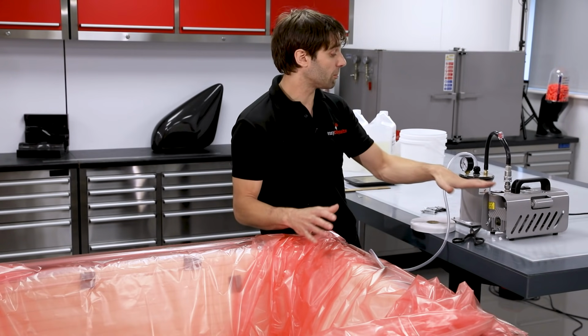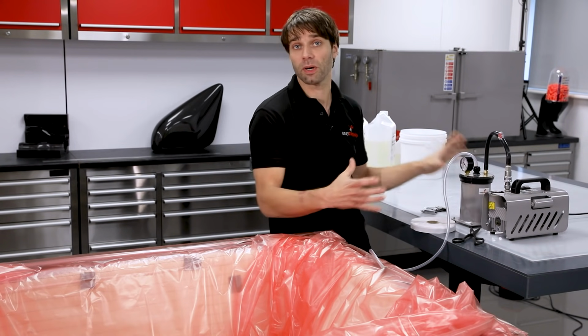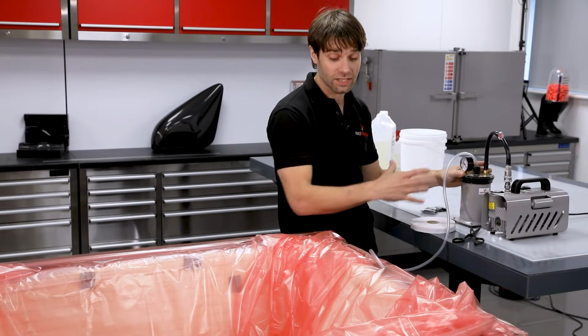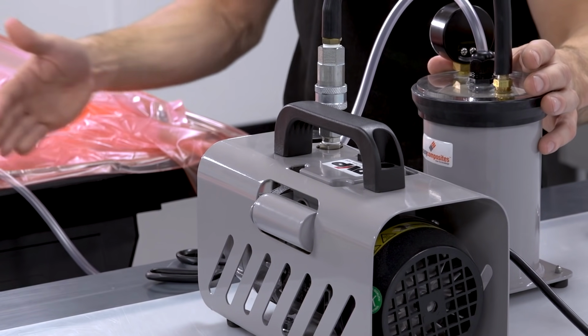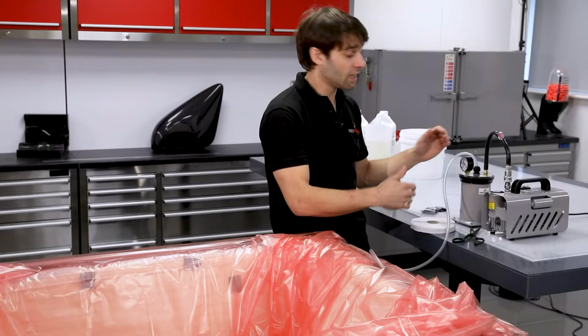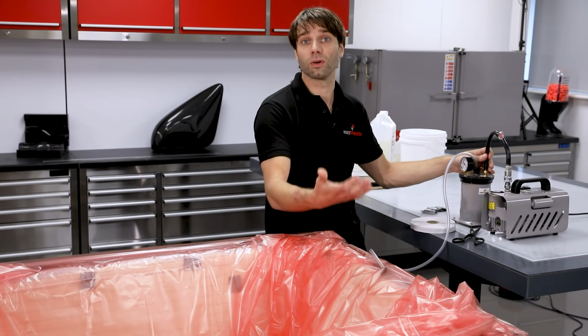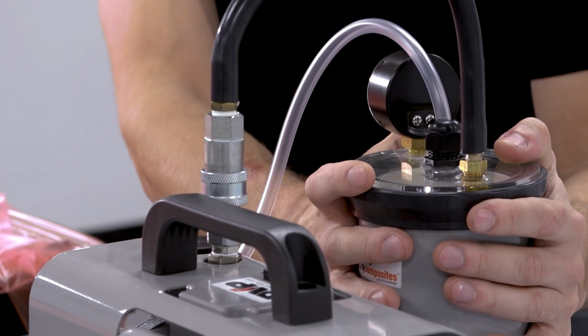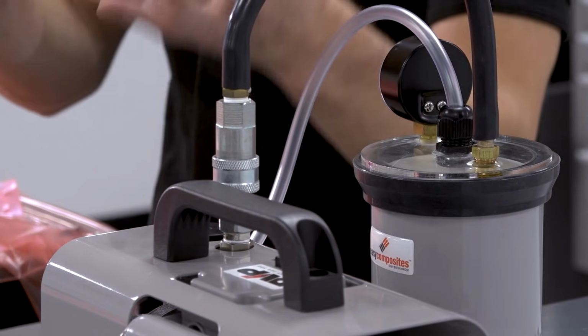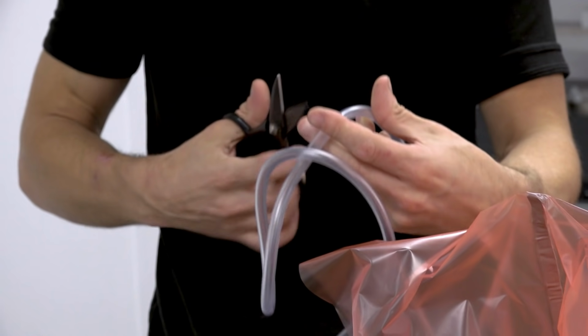In between the part and the pump, we have a catch pot. Now, a catch pot is there to save the pump from damage. With resin infusion, it's very common to have the resin coming up through this line, and if it was to go straight into the pump, of course, that would harm the pump. So this is there to catch that resin before you clamp the line finally and switch the pump down.